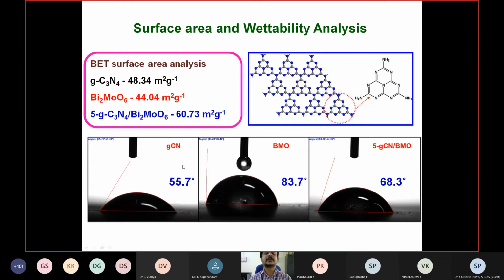Also, just look at this. This is the contact angle measurement. Here the graphitic carbon nitride shows the lowest contact angle. The bismuth molybdate shows the highest contact angle. After making the nanohybrid material, the contact angle value lies between those of graphitic carbon nitride and bismuth molybdate. Why? Because after adding graphitic carbon nitride into the bismuth molybdate, the terminal amine groups in the graphitic carbon nitride easily make hydrogen bonds with water. So that decreases the contact angle of this bismuth molybdate.